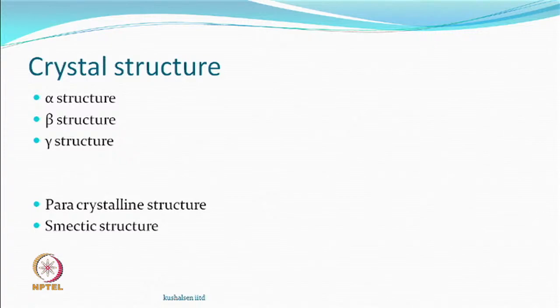Polypropylene, which is also a good material for texturizing, can have alpha, beta, and gamma types of crystal structures. Some materials like acrylic do not show very highly defined, defect-free crystals, and therefore their crystalline structures are somewhere in between — not amorphous and not fully crystalline — what we call a para-crystalline structure. Polypropylene also has another intermediate structure called smectic, where there is some order but the whole region is not totally crystalline.